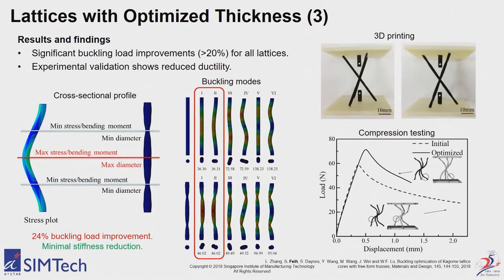And we also validated this experimentally. Again, this was very hard because these are quite fine structures, and to measure all this properly during the test, especially as far as buckling is concerned, things need to be aligned very carefully. So we validated it for the Kagome, but also for the single column, and we got very good agreement with what FE analysis predicted and what the experimental results showed.